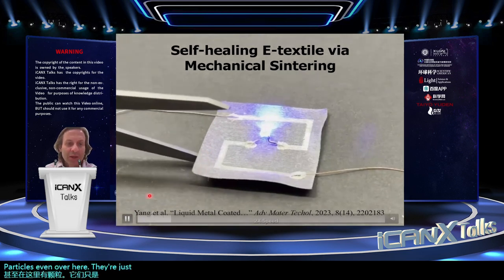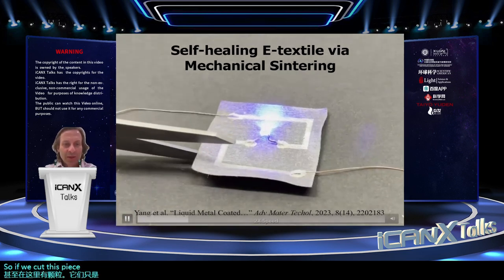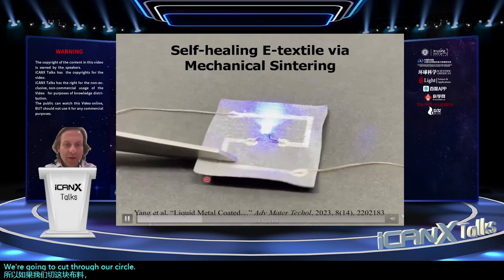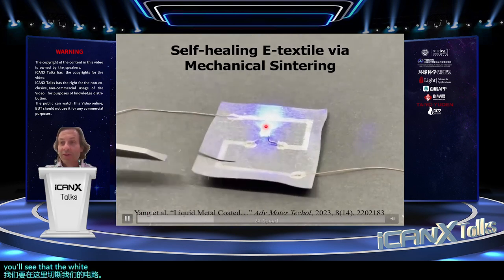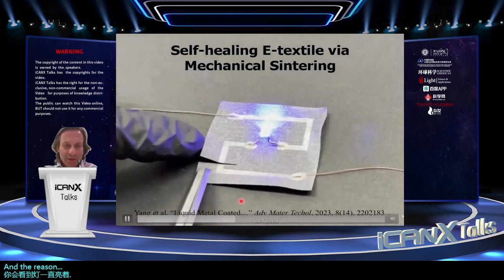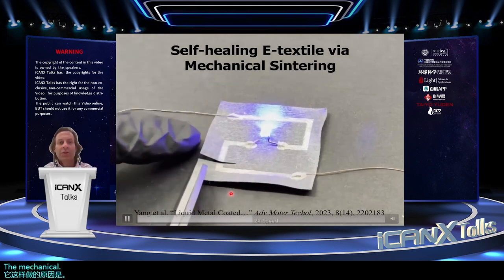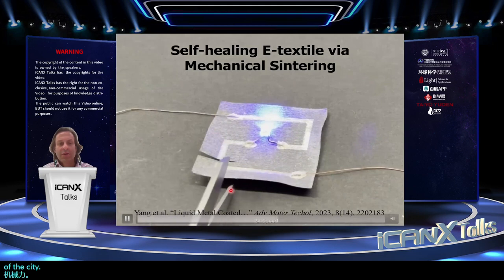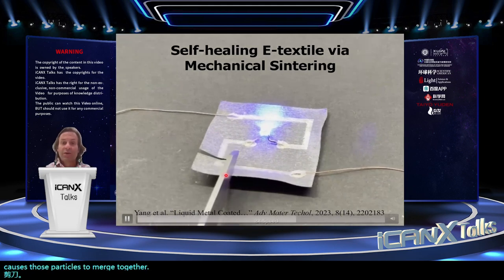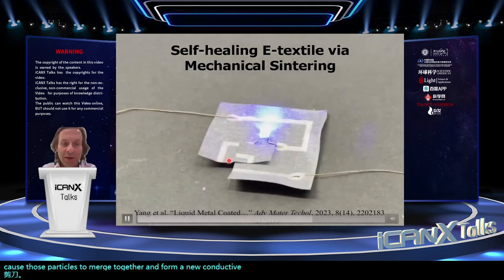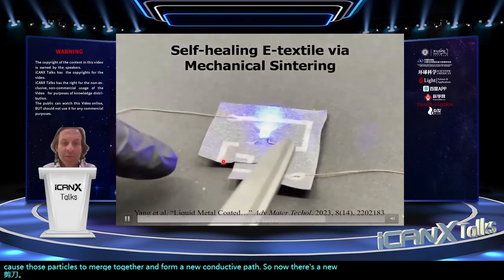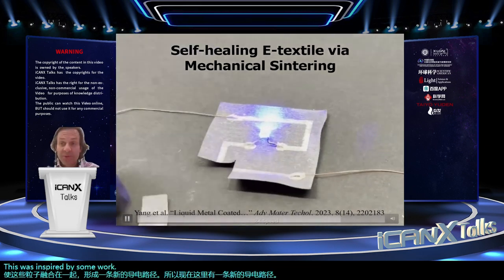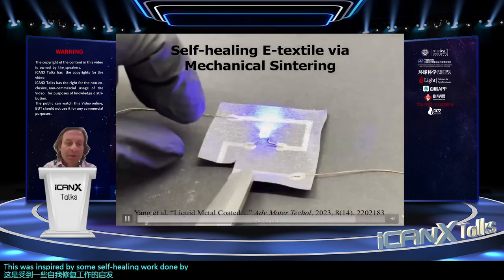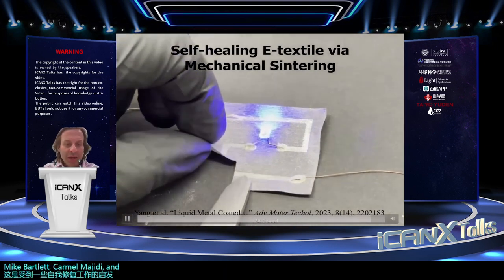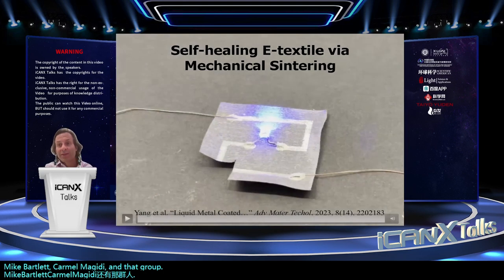They're insulating. So if we cut this piece of fabric, we're going to cut through our circuit right here. You'll see that the light stays on. The reason it does this is because the mechanical forces of the scissors cause those particles to merge together and form a new conductive path. So now there's a new conductive path here. This was inspired by some self-healing work done by Mike Bartlett, Carmel Majidi, and that group at Carnegie Mellon. But here we've applied that same principle to a fabric.